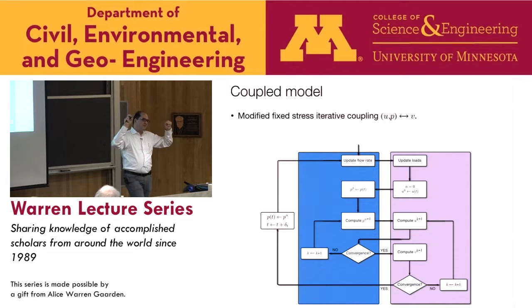Once we have the fluid and mechanical equilibrium, we use this information to update the phase field, and we iterate this. Although we have not been able to formally prove convergence of this scheme, it turns out to be very robust, and we never had a problem of divergence of this pumping problem, where at one step your crack becomes very large and then your pressure drops, so at the next step the crack has to shrink, and so on. So this is very robust.